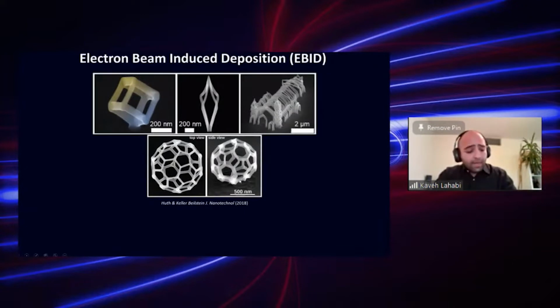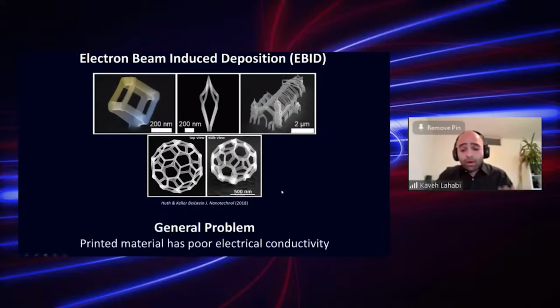However, unfortunately, when it came to the electrical properties, the deposited materials turned out to be not very useful. Because you see, and this is a common problem with all printing techniques, the deposited material is highly disordered and has a poor electrical conductivity. And especially at low temperatures, this gets a lot worse.